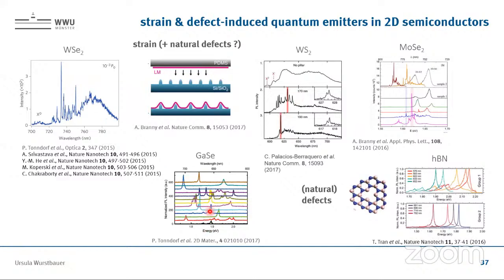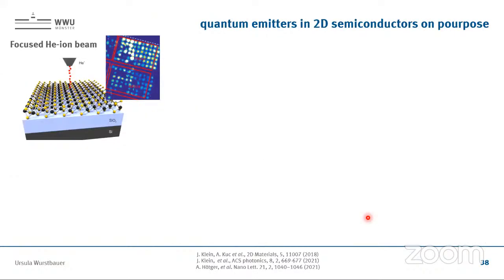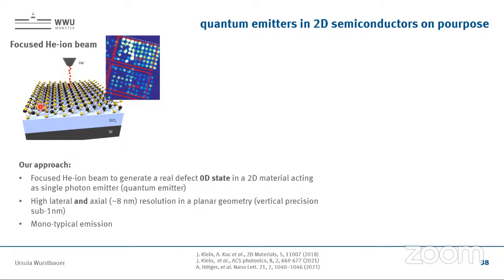And there's another concept which can be pursued, because here the defect is playing the role. And why not use the defect on purpose to generate quantum emitters? It can be done by focused helium ion beam irradiation of these transition metal dichalcogenides. So the concept is we take a helium ion beam to generate zero-dimensional defects in a 2D material, which can act as a single photon emitter.